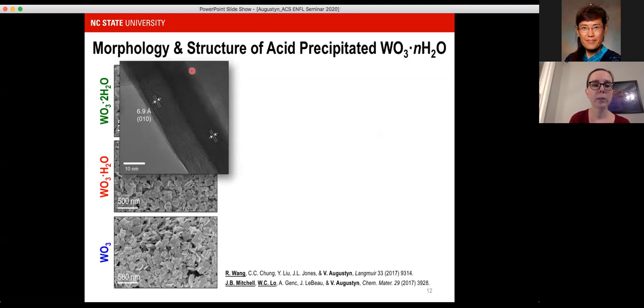So we did cryo-TEM of this material, and it had to be cryo-TEM in order to see this interlayer spacing. If we did it under regular TEM conditions without the cryo cooling, this material starts to transform into the anhydrous oxide. So this is just an important part of doing the characterization in high vacuum environments.